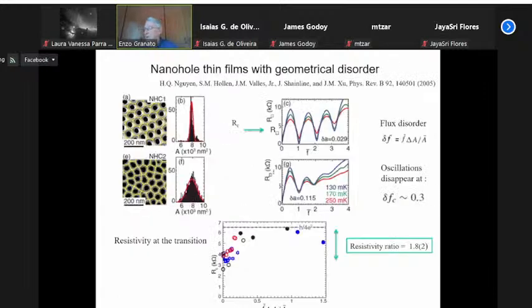Now I would like to consider some experimental data realized in the same system, in which the honeycomb array now has some geometrical disorder, as illustrated in the figure on the left. In the top figure, there are almost periodic lines. The yellow lines here are a Voronoi construction to obtain the areas associated with each of the holes. The area is almost constant; the probability distribution of the areas is very sharp. Here is a sample constructed in such a way that the holes are located in different positions, so the areas around each hole are different. If you look at the probability distribution of the areas, the distribution is very wide, so there is a lot of disorder.